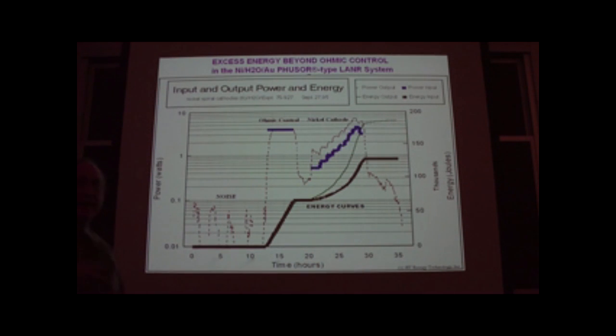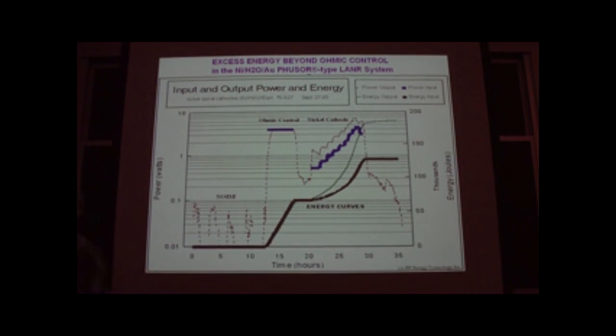So here we're running a nickel system over time. We're looking at the power input, which is here. Here's our background noise. As I told you, we always measure noise before we run the experiment. So this is in log watts here. We do an integral to get the total energy of the system, which is here, up from 0 to 200,000 joules. So here, for example, we wait 10 hours and measure the noise in the system.